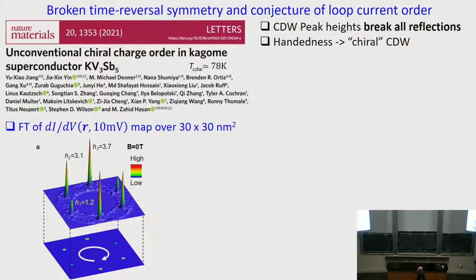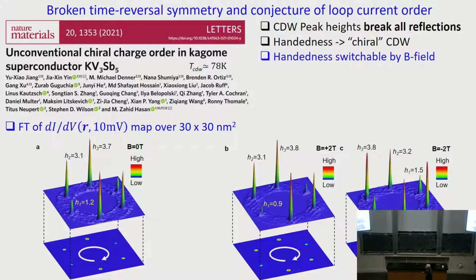But that's something unusual. So we thought maybe, could that be something that we can use to say it breaks time reversal symmetry? And the answer is no, because I can have a structure that breaks all reflection, and it will be a chiral structure. So we apply a magnetic field, then something is really interesting. You apply a field in one direction, plus 2 Tesla pointing upward, and there is one kind of chirality. When you flip the field direction to pointing down, the chirality changes, becomes right-handed. So you go from weak peak to intermediate to strong peak. So it is that chirality, that sense of handedness, gets flipped by magnetic field, which tells us this state might be broken time reversal symmetry.